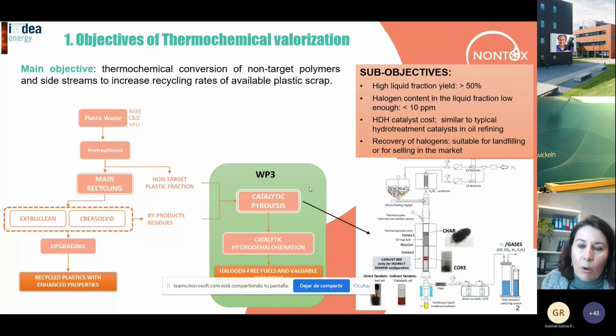wastes. The objectives proposed in this work package were to have high liquid fraction yields, above 50 weight% regarding the initial feedstock; halogen contents low enough for this oil to be marketable; and using catalysts that are not very expensive, that are competitive. Finally, the objective was also to recover as much as possible of these halogens in order to allow the landfilling of the charred residues, for example, or to sell these compounds in the market.